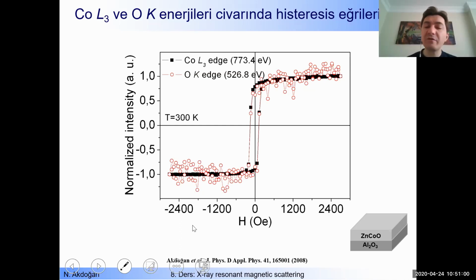Okay. So you can also carry out low temperature experiments, and indeed we did low temperature experiments for many materials in the past. But in this case, even at room temperature, we have a very nice signal from the cobalt and a very nice signal from the oxygen. So it is not necessary to go to low temperatures. If you cannot see a good signal at room temperature, of course you can go to low temperatures. And for sure, at low temperatures, the magnetization will be higher for ferromagnetic materials.